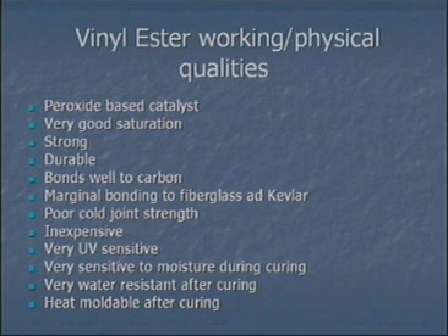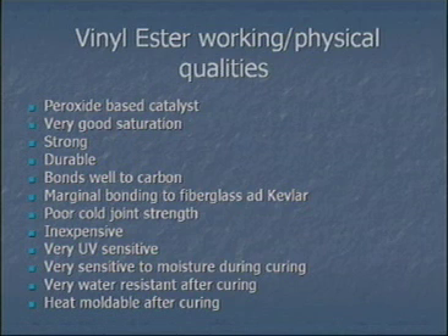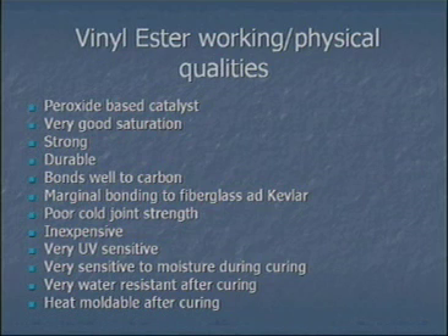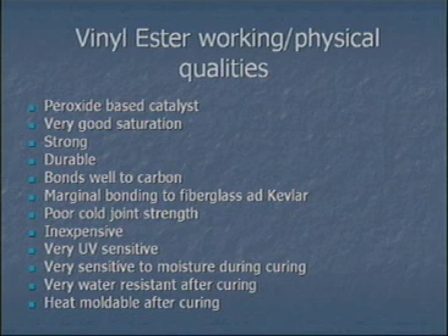It has marginal bonding ability to fiberglass and Kevlar. So if you're going to use this to make a fiberglass socket, it's probably not the wisest idea. We have a sample in the O&P lab of some different layups, and you'll see that the ones that were bonded with fiberglass and the vinyl ester are not very strong at all. So you may not want to use this for fiberglass. It has poor cold joint strength, so if you're doing a cold joint and you want to bond the resins together, it's probably not the best one to use for that either.